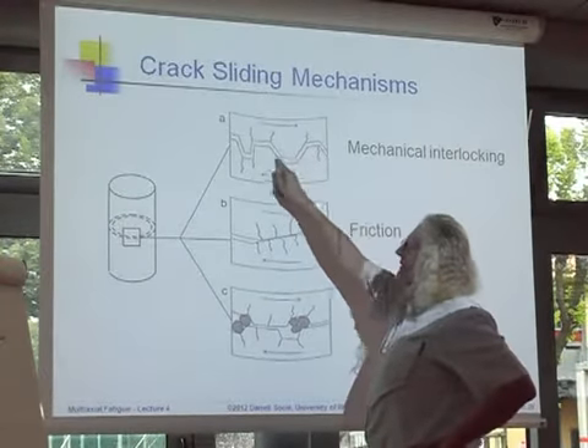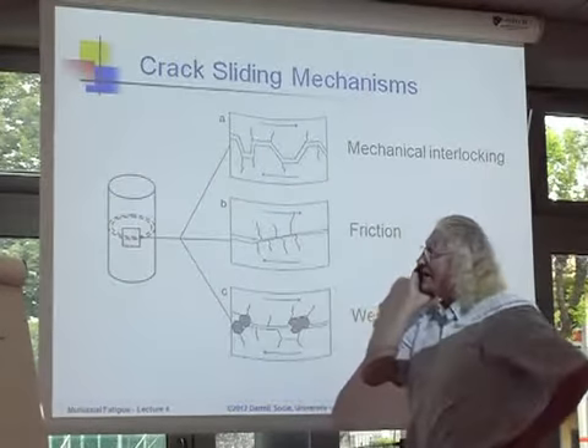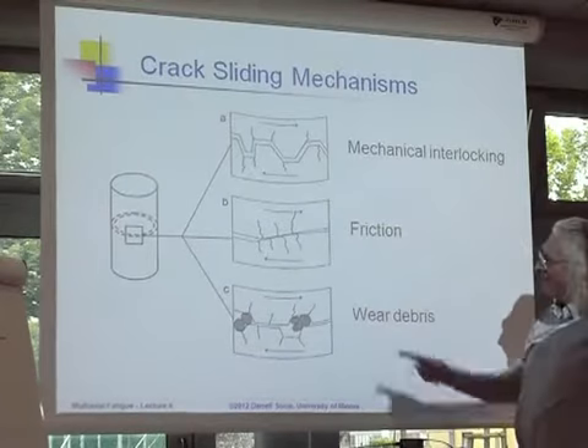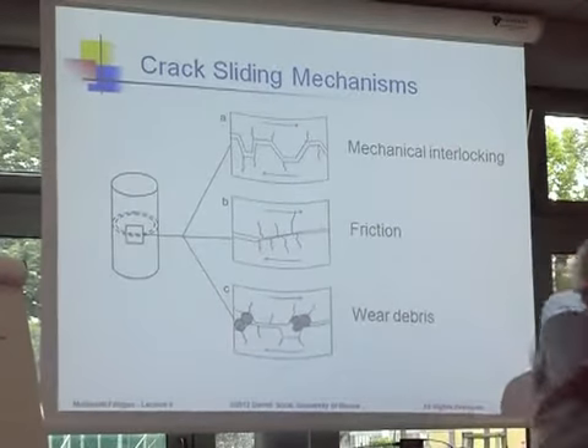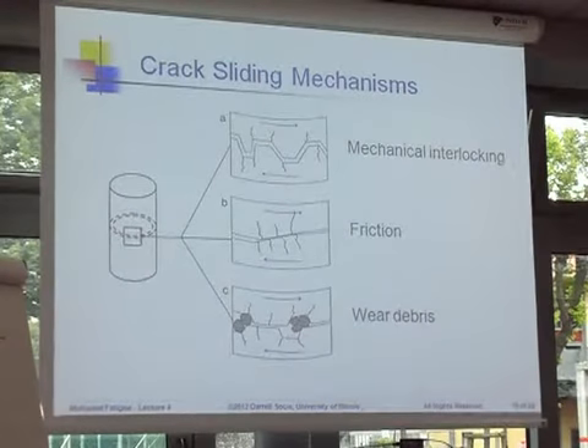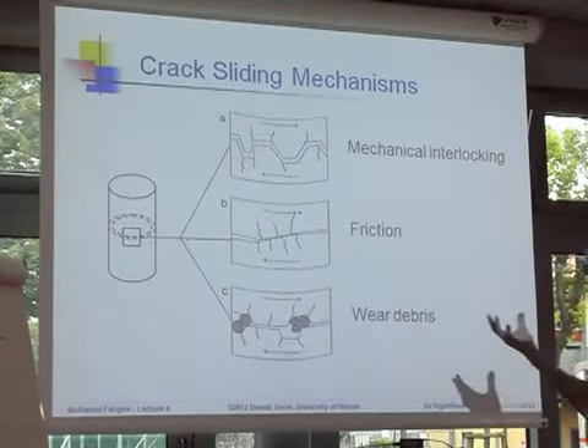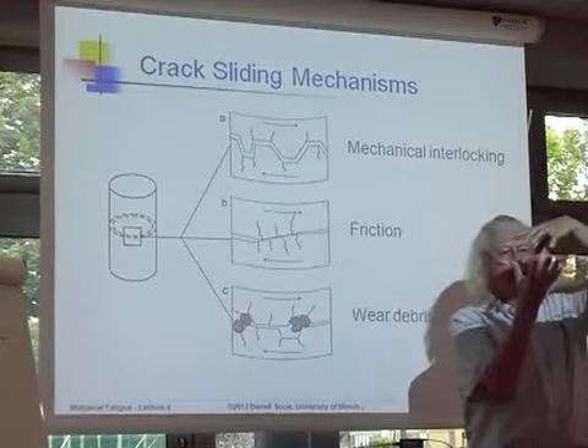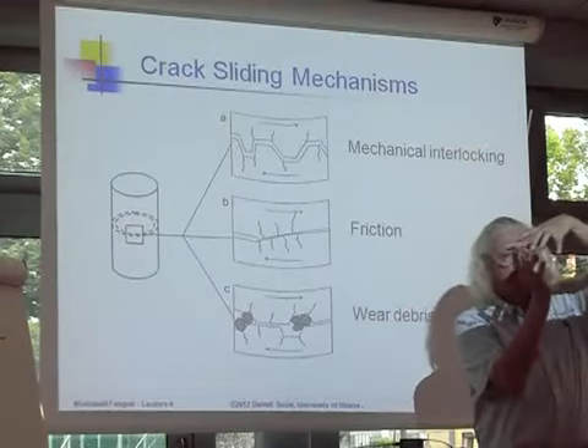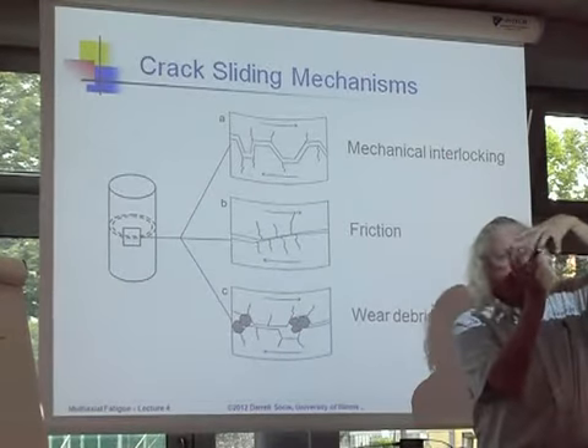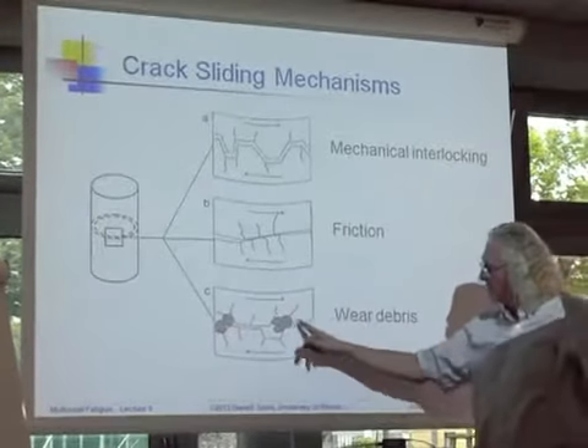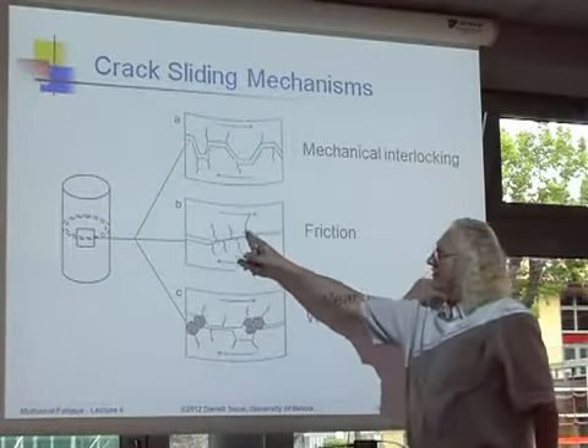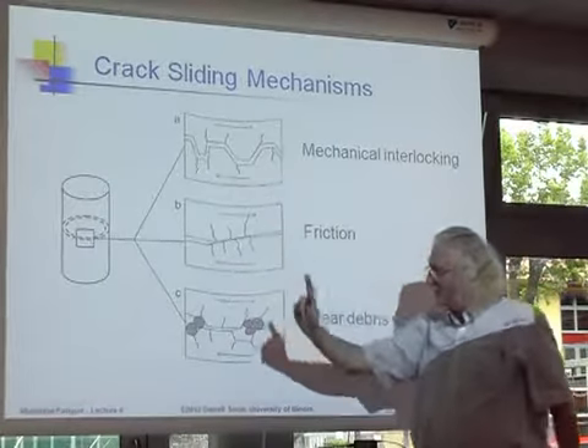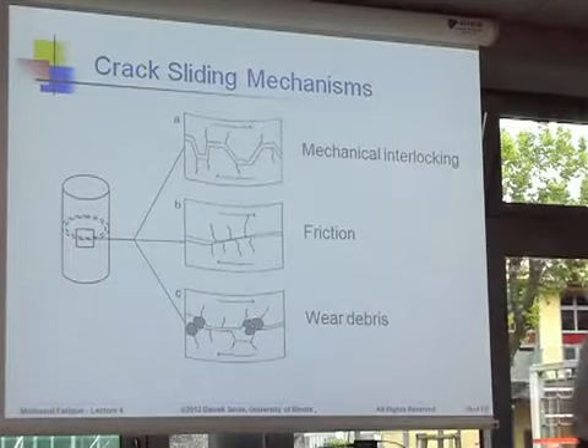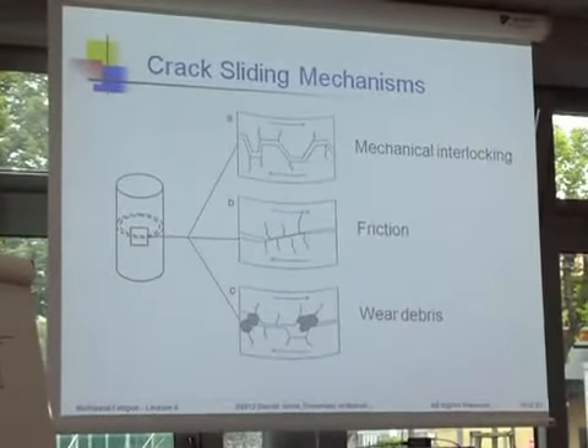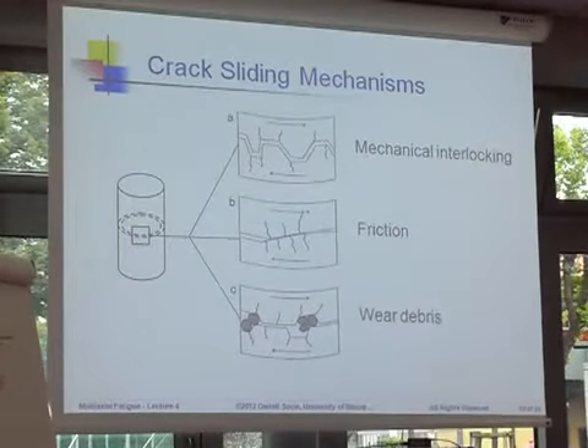Think about the mechanical interlocking that happens. And if you don't like this picture, then think about all the friction that must be there. So quantifying the friction is very important. And then think about that if I really have a fatigue situation that's cycling back and forth, then I will also generate a lot of wear debris particles because of all of this friction and all of this interlocking. And so this creates even more debris. This is the essence of understanding mode 2 and mode 3 fracture. This interlock.